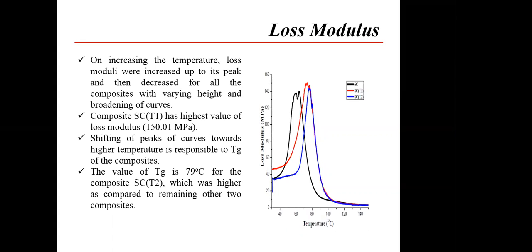Which energy is dissipated, that is loss modulus, and the energy saved for future use, that is storage modulus. So we can get the value of glass transition temperature from the loss modulus curve. This curve is also a plot of the variation in loss modulus with respect to temperature. Temperature is near about 70 degrees Celsius. At 70 degrees Celsius, we get our glass transition temperature value, near about 79 degrees Celsius for SCT2.